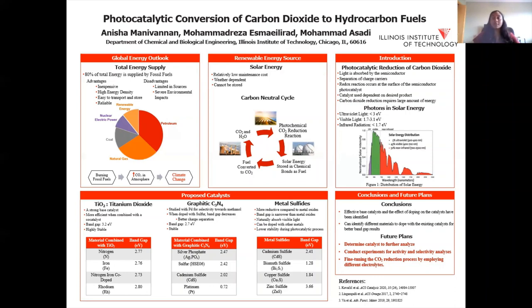The doped metals help diminish the charge recombination by acting as an electron sink, which then traps the electrons and stabilizes the charge separation. When the charge separation is stable, the photocatalytic properties of the material are improved. Nitrogen, iron, and rhodium are promising materials to be combined with titanium dioxide to bring the band gap down.